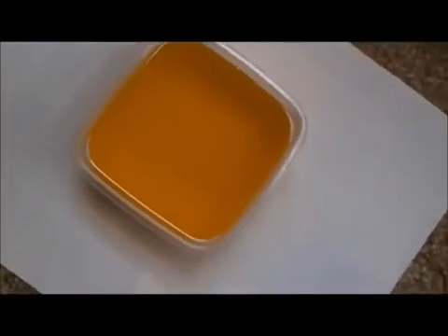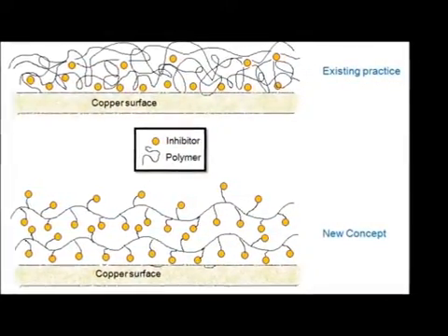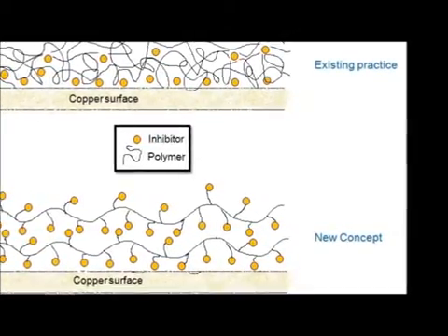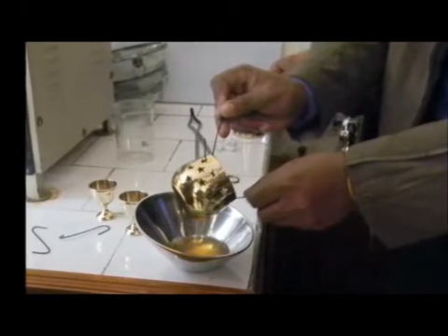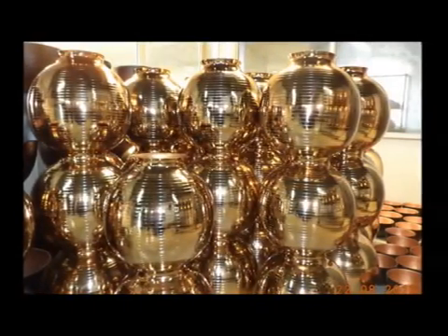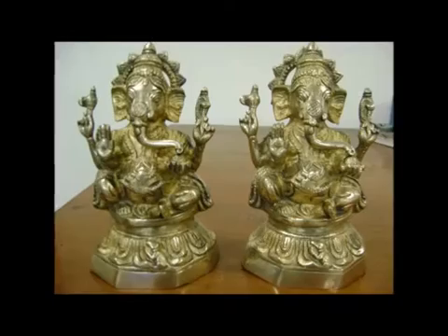The polymer contains active corrosion inhibitors chemically bonded to an acrylic polymer backbone and has strong affinity to adsorb chemically on copper surface. The anti-tarnishing lacquer is a one-component, fast-drying lacquer that provides a durable finish, resistance to water, acid and alkali environments. The coating is non-toxic and free from lead and cadmium.